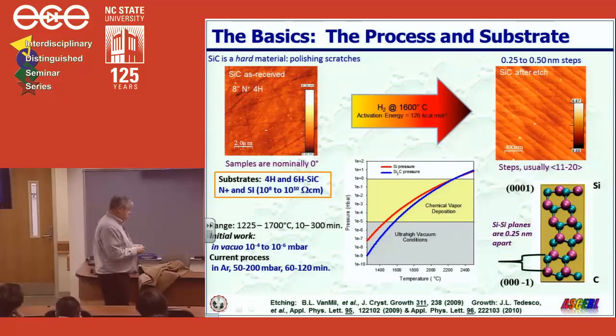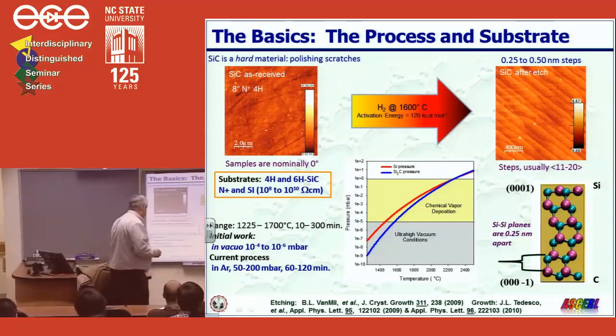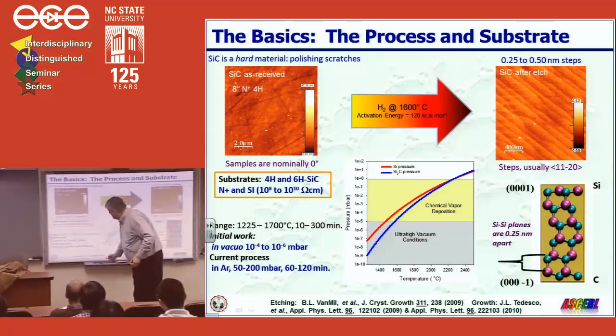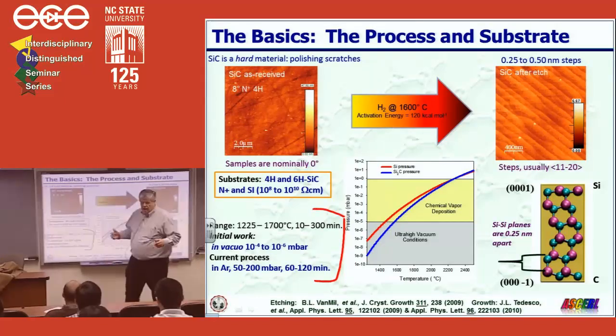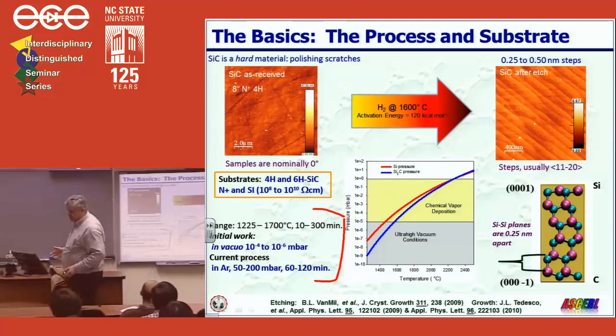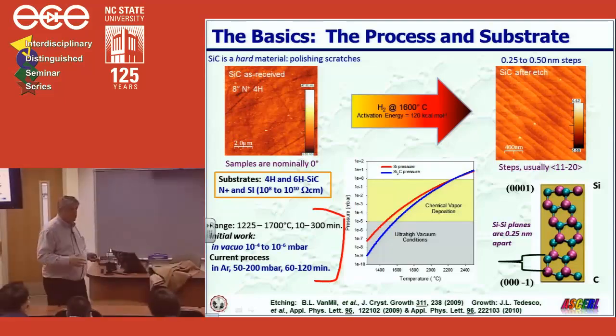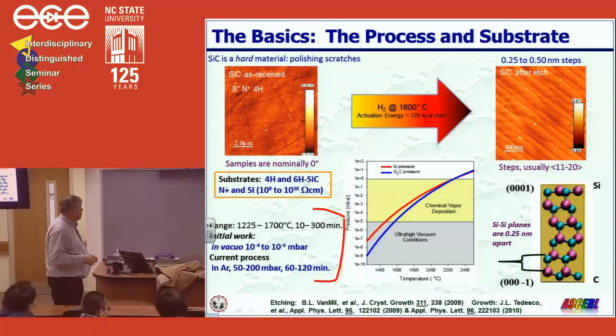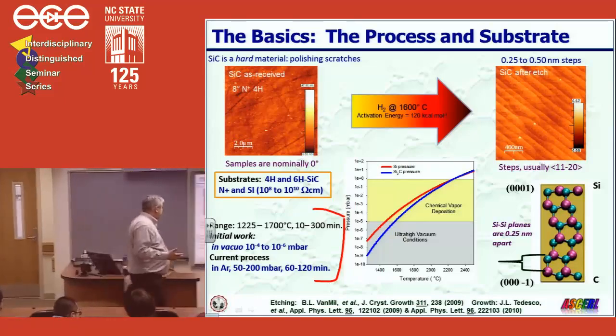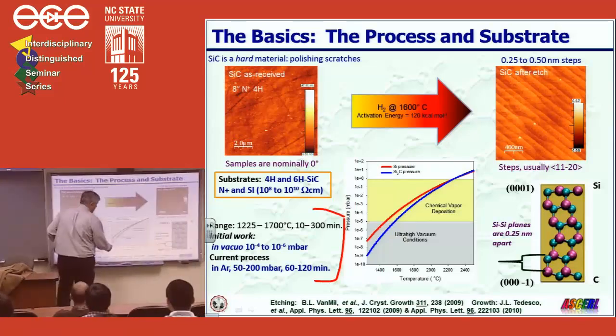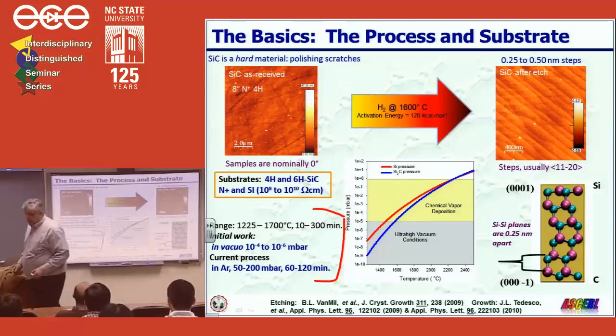Now, we do our work with graphene. We have a processing conditioning range. We looked at a range of conditions shown here. We found what the optimal conditions were for various pressures of argon flow. We found that using argon gives us more uniform layers than using a lower vacuum. And you can understand why all of this happens by just looking at the phase diagram in this sublimation chart for a given temperature of about 1600 degrees. Notice that we have to be able to sweep away the silicon using a pump system on the order of 10 to the minus 5 torr, and then the carbon is left behind and forms the graphene. So it's actually quite straightforward, and anyone could do this in their basement.